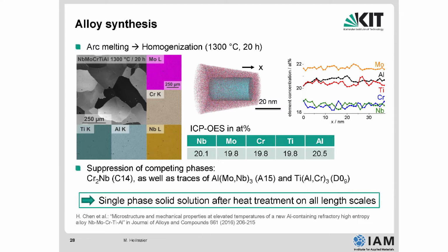For example, overall chemical composition by ICP-OES indicates that the chemical composition is quite well met for this quinary alloy system. But we also do chemical composition on an atomic length scale, and this is what Manuel also did with us, not in this case, but in another case. This is atom probe tomography. Here you see the scale, 20 nanometers, and when you do the chemical analysis, you see that the elemental concentration is quite constant. It's a little bit farther away from each other than here, but again, it scatters around 20 atomic percent. And by doing so, we get a single-phase microstructure by suppressing the competing phases which are shown here.